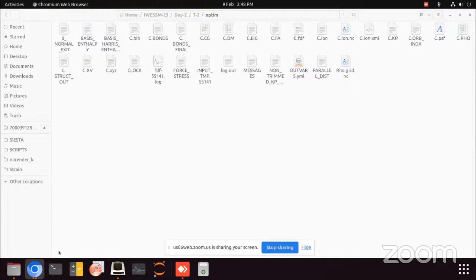So many people just use some default k-points and mesh cutoffs and give the result, and that is not good. We generally follow accuracy. That's why we optimize the system using this. Otherwise, in many papers you can find the mesh cutoff is about 200 to 250 and k-point about 5 to 7. And for the lattice variation and final optimization with some CG steps they can do it. But we have to optimize the system by using this optimization process of these parameters.